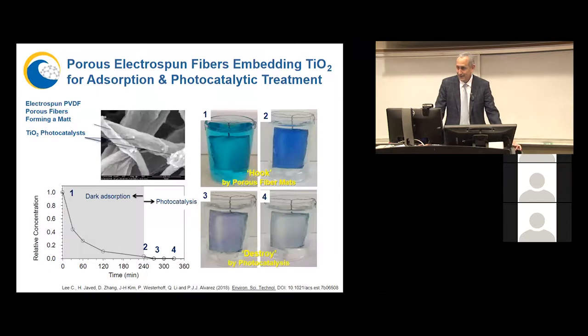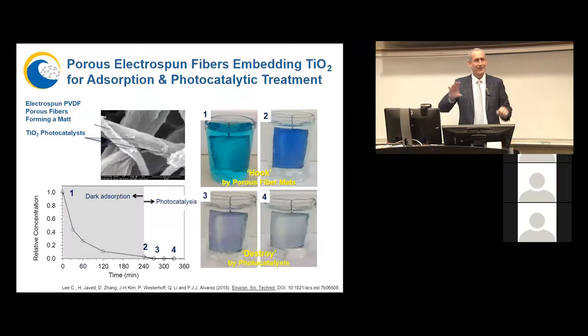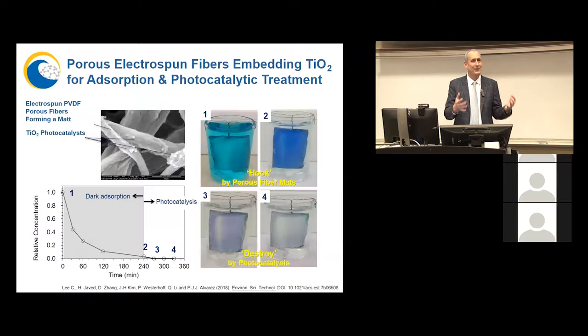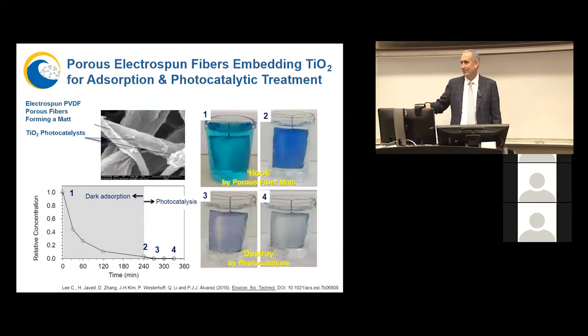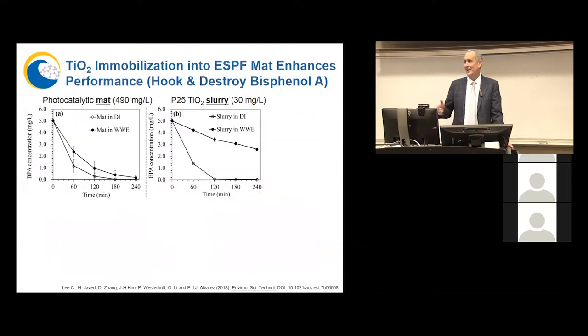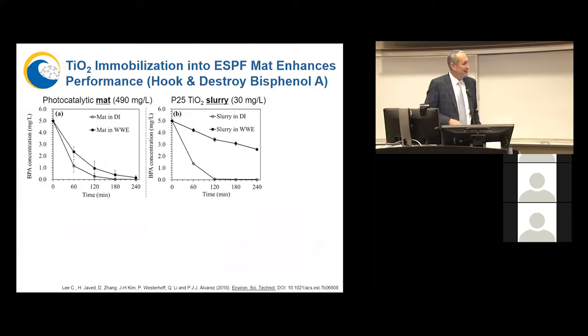And in some cases, you want to uncouple absorption and degradation. For example, if you have really murky wastewater and you just want to fish out the pollutants and degrade them under more favorable, higher transmittance conditions. But of course, for secondary effluent polishing, as I was showing you later, to destroy endocrine disruptors, you don't need to separate them. You can do it simultaneously. And what we're doing here is we're comparing the ability of this photocatalytic mat versus a slurry reactor. This is the common way that we apply right now, TiO2, to degrade bisphenol A.